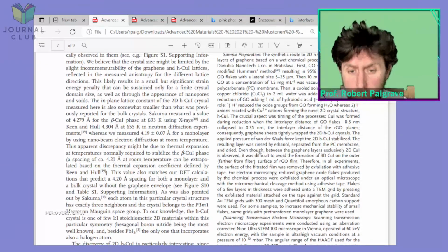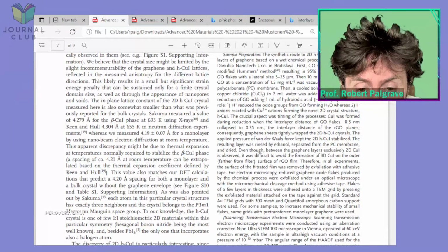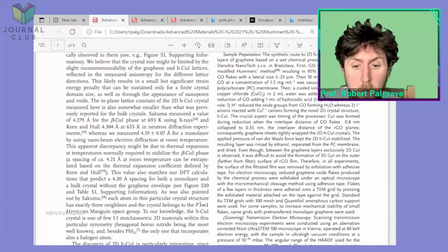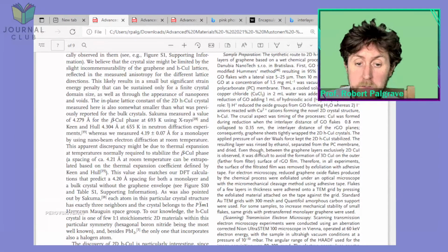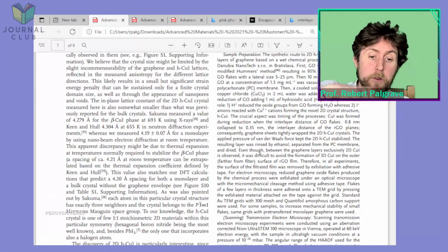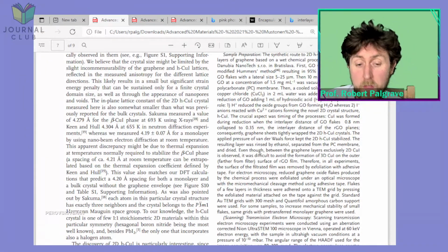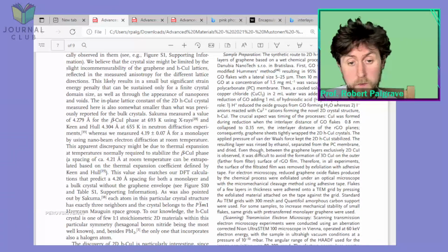So what do they do about that? In all experiments, the surface of the filtered film was removed by exfoliation with adhesive tape. Okay, so they remove it by sticking tape on and pulling the tape off, and they're saying that that removes the 3D portion of the cuprous iodide.